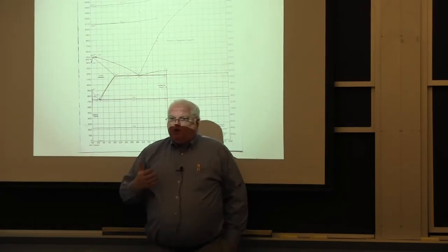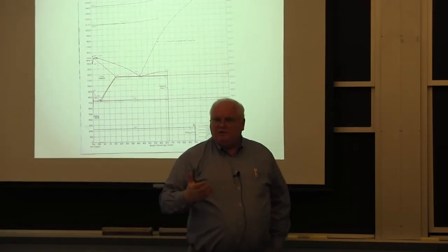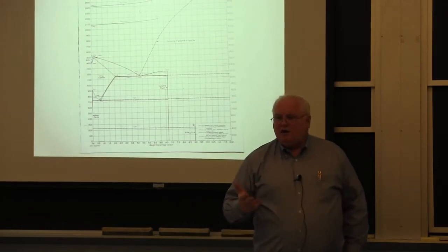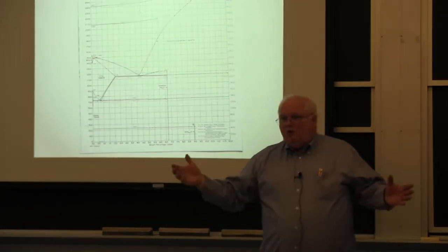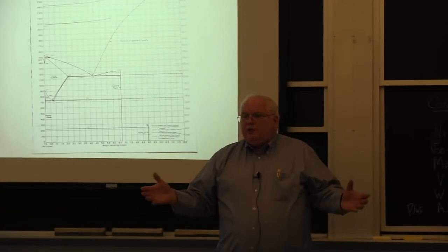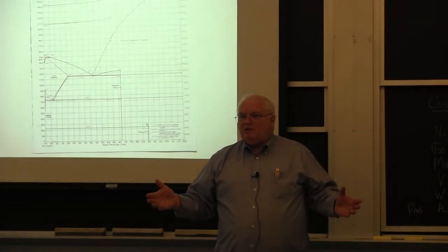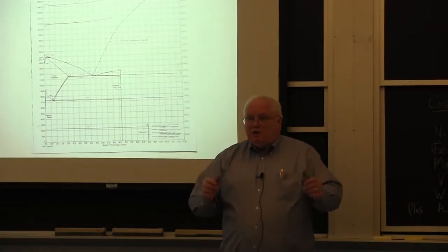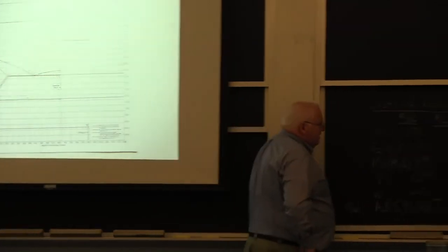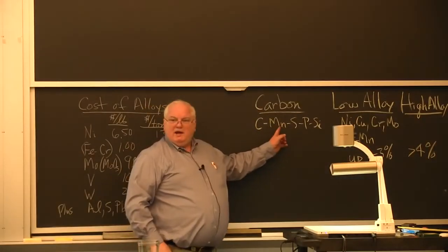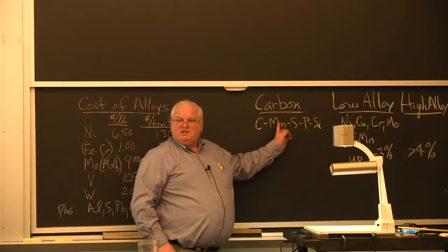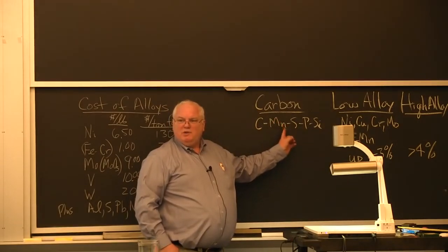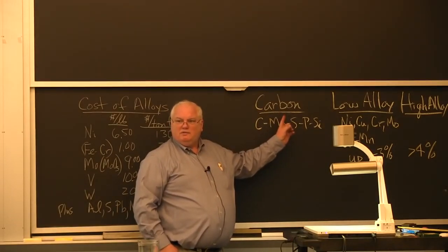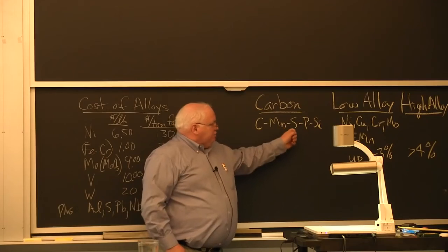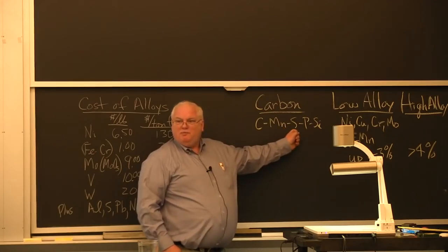And so you'd form liquid iron sulfides on the grain boundaries, and they call it hot shortness or hot tearing. And when you try to roll or forge the steel, it just crumbles into pieces because of the liquid iron sulfide. And someone learned if you throw some manganese in, the manganese will form stable manganese sulfides that melt above the melting point of steel. So manganese is merely a way to tie up the sulfur impurity that comes from your coal.